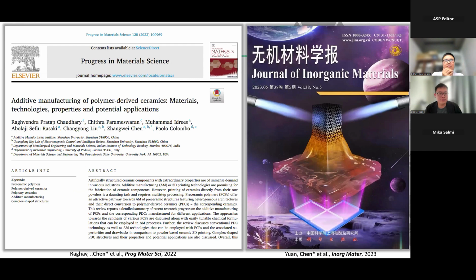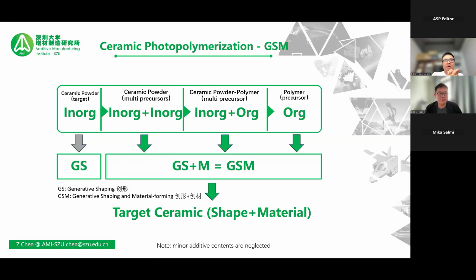So it's interesting that the whole procedure can be demonstrated here. And I have a very minor summary of what I have been talking about previously. Starting from inorganic material like ceramic powder, which is the target powder from the beginning to the end, it's just generative shaping by 3D printing. It means that the 3D printing is only to create a shape. There's no possibility of generating new material, at least the majority of material stays the same. Then we propose A plus B methods, the generative shaping and material forming method, like a combination of inorganic material with organic material. And finally, we have the precursor method using PDC. It's all organic material. So this is the generative shaping and material forming.